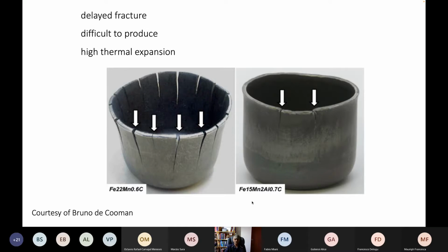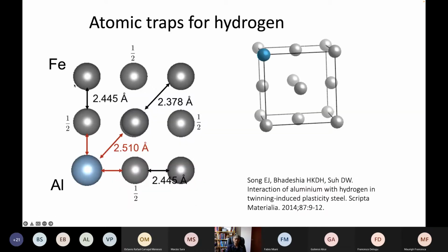There are various models for this, but one which is really interesting is that the aluminium atom causes a localized expansion around it. So for example, if this is our face-centered cubic unit cell, and these are the face-centering atoms, then the distance between the iron atoms and the aluminium atoms is larger than between the iron-iron atoms.